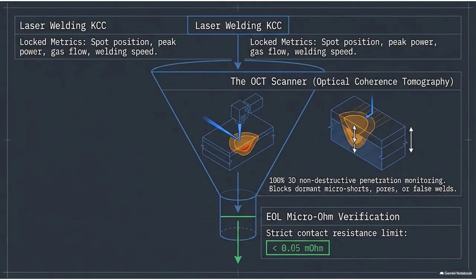Okay, so if the laser's power dips for literally 1 millisecond, potentially creating a poor or a cold weld like we discussed earlier, the SPC system detects the parameter deviation instantly, aborts the sequence, flags that specific battery module as defective, and automatically routes it off the line to the scrap heap. Just immediately scrapped. Immediately. That covers the machine's parameters, but how do you verify the actual liquid metal?